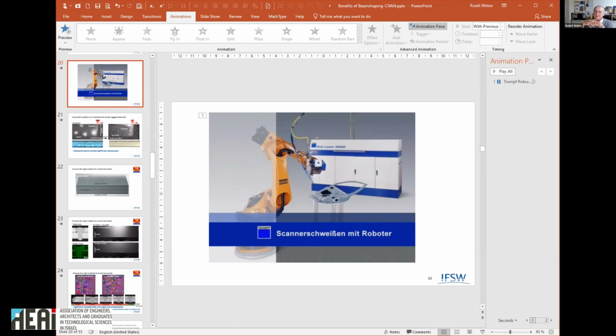Just one additional remark, there was a PhD student at the IFSW who mainly solved the problem. If you do stitching, it always needs a certain distance until you get the hot crack. So we do some stitching. If you stop the process before the crack appears, you can really get nice and crack-free welds. That's possible by the process, but by taking these multi-core fibers or so, at least we didn't succeed in doing it.